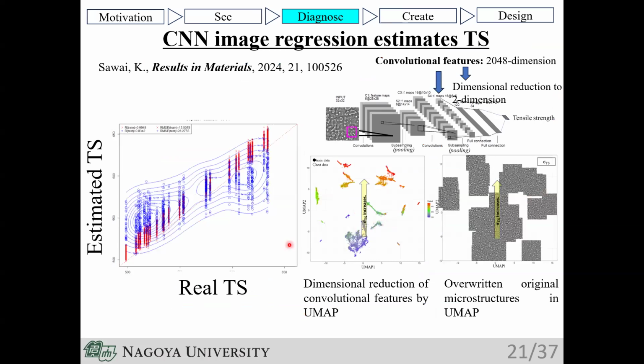This figure shows how accurately the CNN estimates tensile strength from a micrograph. For not only a training dataset shown in red, but also a test dataset shown in blue, which was not used for training, the CNN predicted tensile strengths with accuracy R higher than 0.83 for test data. When my student, Mr. Sawai, demonstrated this result to me, I was a little bit surprised and shocked, because no traditional metallurgical descriptor extraction was used at all to demonstrate microstructure-property linkages. Only a computer knows the important microstructure descriptors to yield tensile strength.